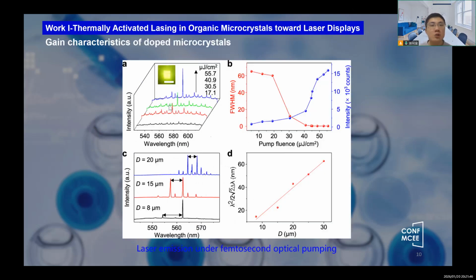Benefiting from this regular morphology, a nonlinear relationship between pump power and emission intensity under optical pumping was observed, indicating laser emission in this system. By fitting the mode spacing in the laser spectrum at different sizes, the laser resonance mode in the microcrystals was determined to be a whispering gallery mode.